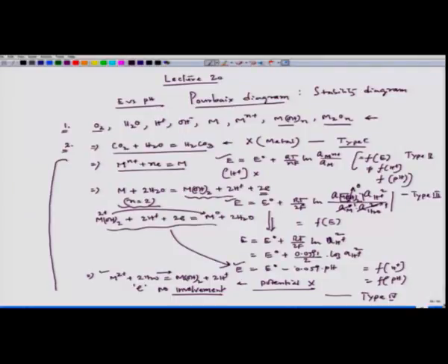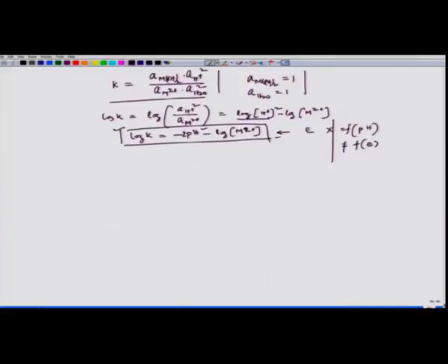These reactions we are considering to happen in the aqueous system, and that would lead to plotting E versus pH, and that would give us the Pourbaix diagram. Interestingly, the Pourbaix diagram will not be complete if we do not consider 4 reactions involving only oxygen, dissolved oxygen of course, hydrogen, hydrogen ion, and 2 other species, OH minus and H2O.